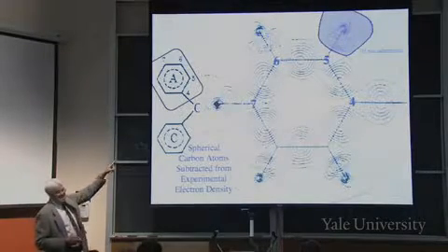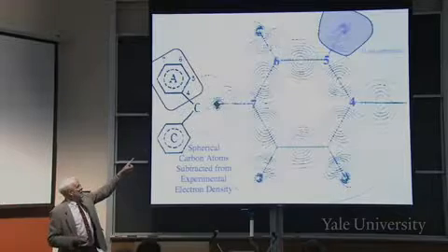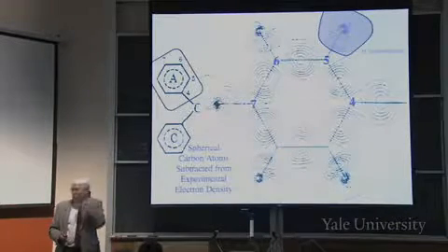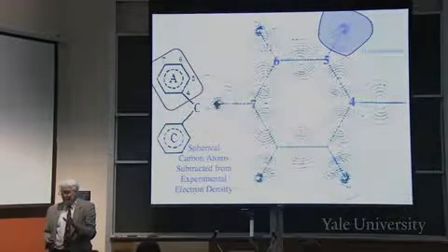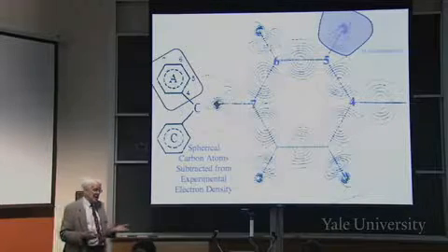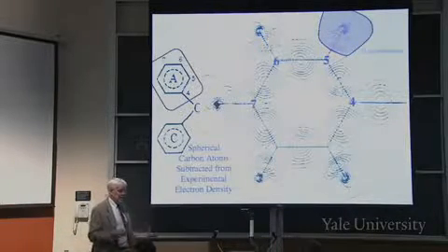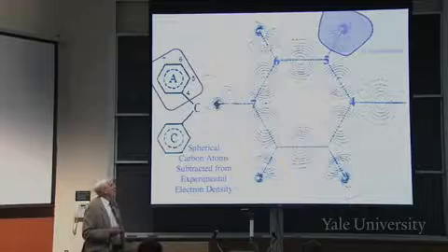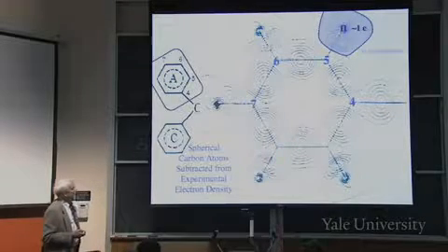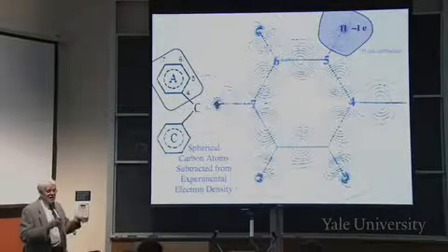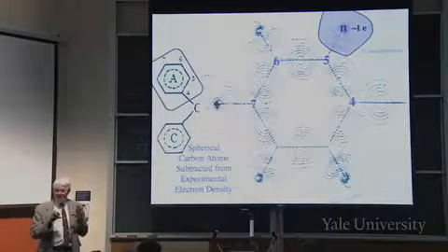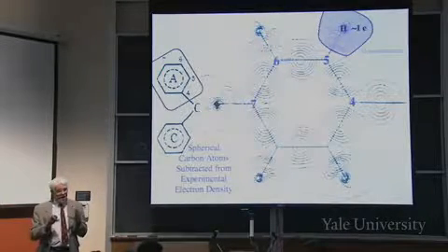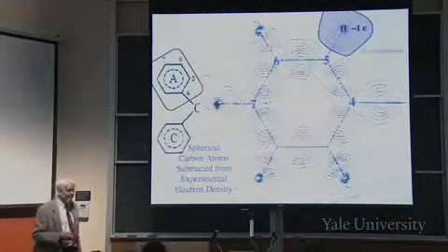There are some very dense contours right in the middle up there, and that's the hydrogen, which was not subtracted, right? So it's the biggest game left in town once you've subtracted the spherical carbons. Okay, and the total amount of intensity in that region is 1 electron, which is what you expect.